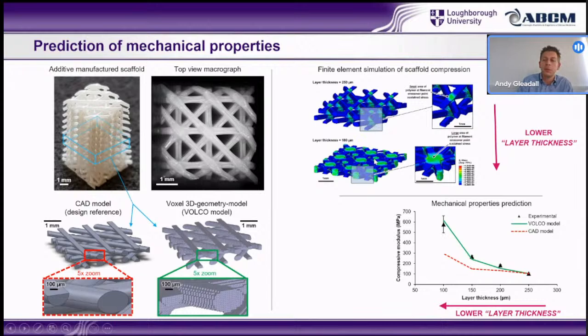The bottom one's not smaller because I've compressed it more in FEA. That's the actual printed structure. But on the very bottom left, you can see the typical way you would potentially get a prediction of mechanical properties, which would be to produce a CAD model based on the toolpath using, say, an assumption of cylindrical or oval filaments or something.